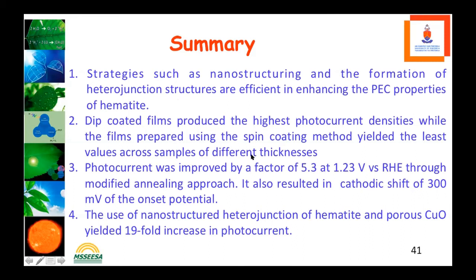And the photocurrent was improved by a factor of 5.3 at 1.23 volts versus the reversible hydrogen electrode. It also resulted in a shift of 300 millivolts of the onset potential. And this use of nanostructured heterojunction of hematite on porous copper oxide gave a 19-fold increase in the photocurrent. So all that we are looking for is to increase the photocurrent